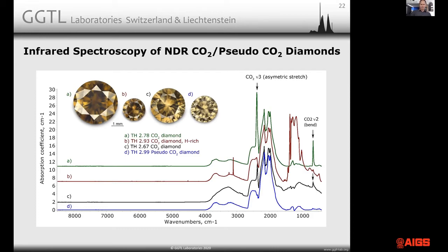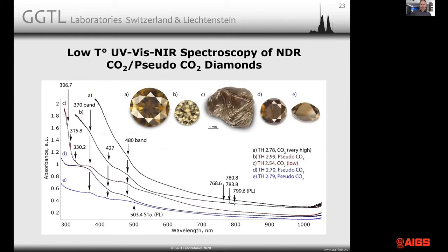Here is the absorption spectroscopy of them. We have 3 pseudo CO2 diamonds and 2 CO2 diamonds. And you can see that the spectra are very, very similar. They all contain a weak 480 nanometer band, a band that has been assigned to oxygen defects in the past. They all have a 427 nanometer band, something we also see correlated to the 480 nanometer band. So this is the typical kind of spectrum of a CO2 and pseudo CO2 diamond.